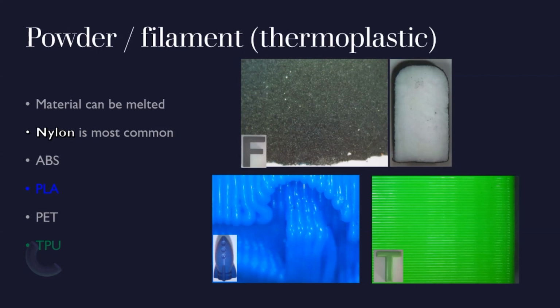Another material that is a thermoplastic 3D printing material is ABS, acrylonitrile butadiene styrene. This is commonly used in fused filament fabrication, or FFF. ABS filament is extruded through a nozzle that is at an appropriately hot temperature, much like a hot glue gun works. ABS is considered non-toxic, which is a good thing because that's what Legos are made of, relatively stable under museum conditions, and not prone to off-gassing.